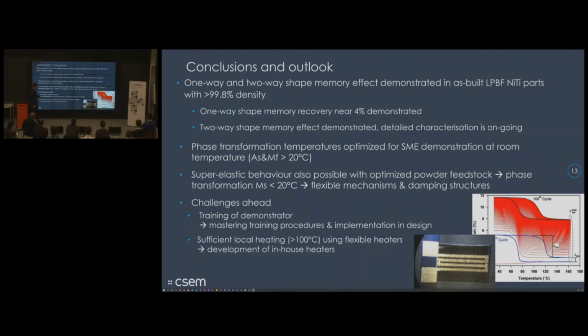Also, it's important to have a sufficient local heating. Nitinol is a relatively good conductor, so in certain sizes, it's not efficient anymore to use joule heating. And for example, in-house in CSEM, we have development of our own sensors using inkjet printing, but it can be used also for printing locally, using inkjet printing, flexible heaters that we can apply to locally heat the structure only where we need it. And finally, the stability of shape memory effect is also very important. There are actions that can be taken on material or on design side.